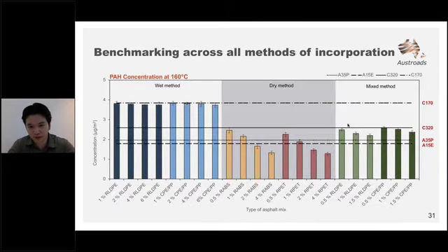To summarize the differences in the different incorporation methods, a graph here is plotted from basically all of the asphalt mixes, including their respective benchmarks. All recycled plastic modified asphalt mixes showed lower PAH concentration values compared to their respective benchmarks. Note that the wet method is meant to be compared against C170, while the dry and mixed method is meant to be compared against C320.